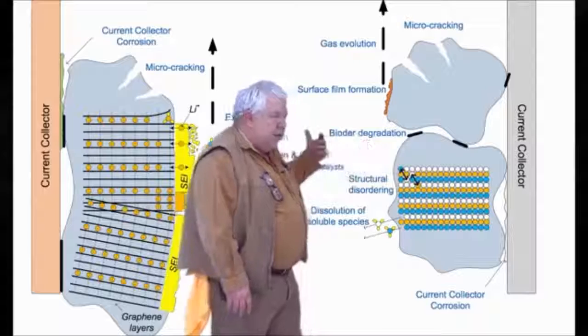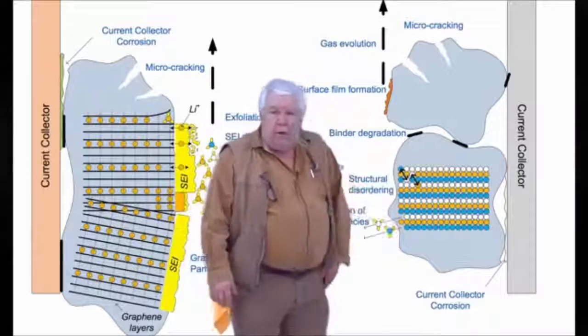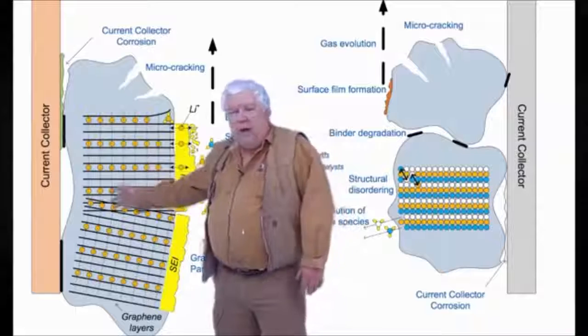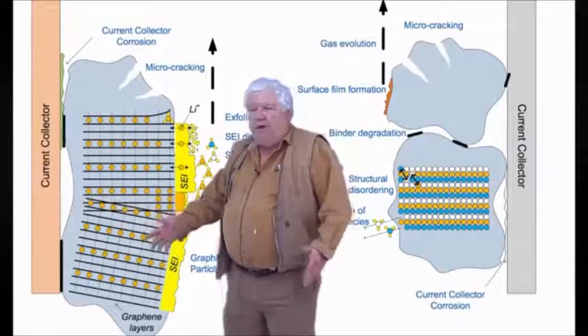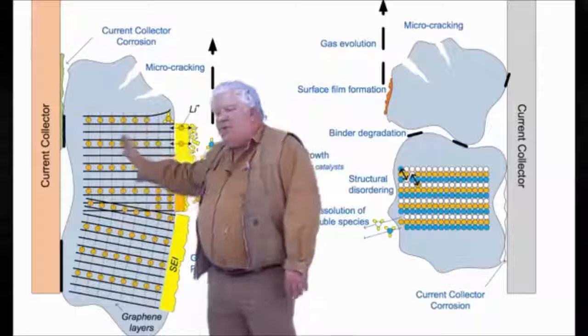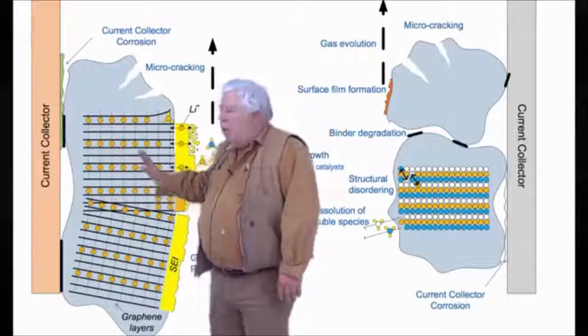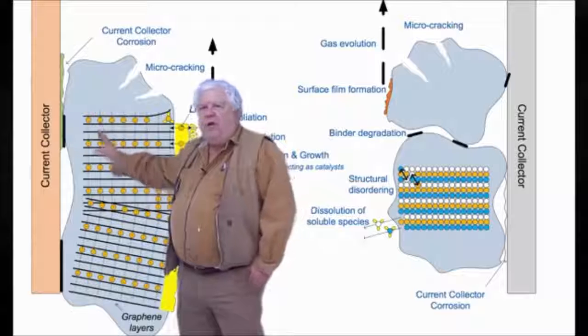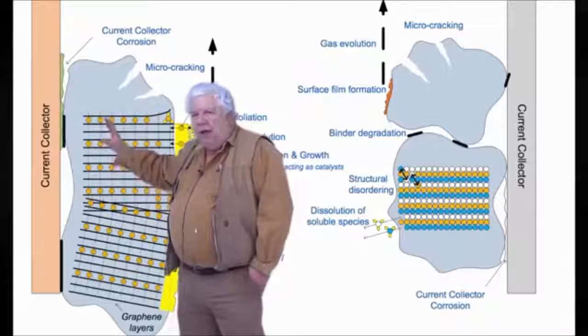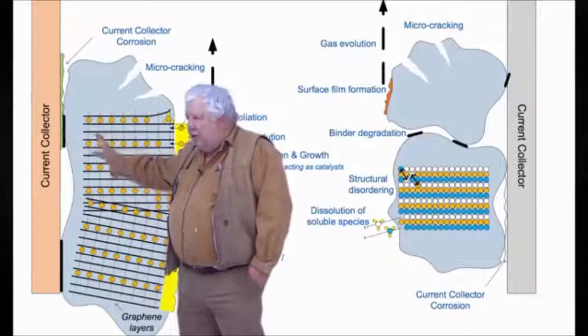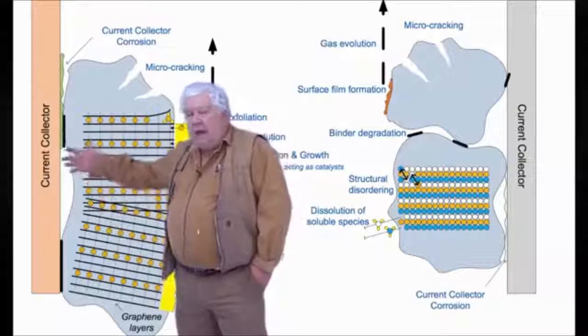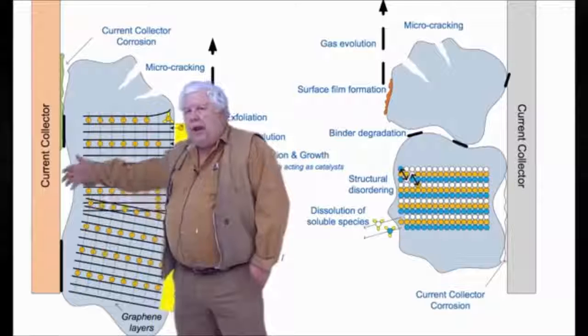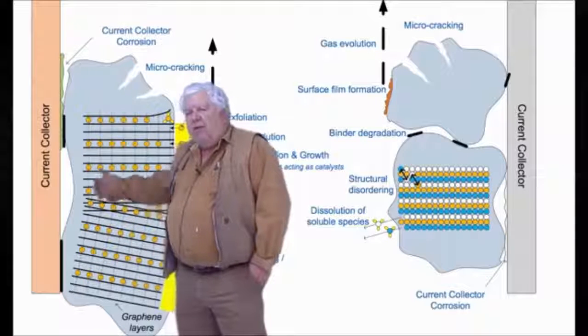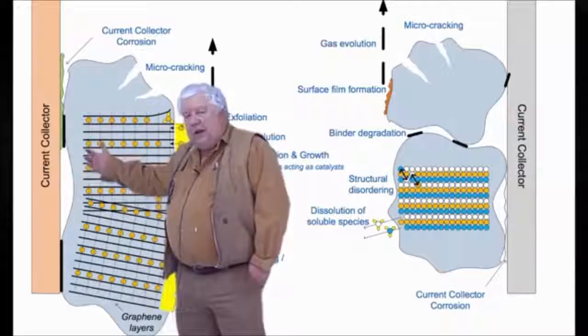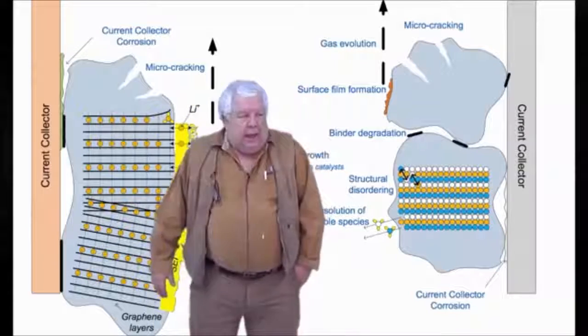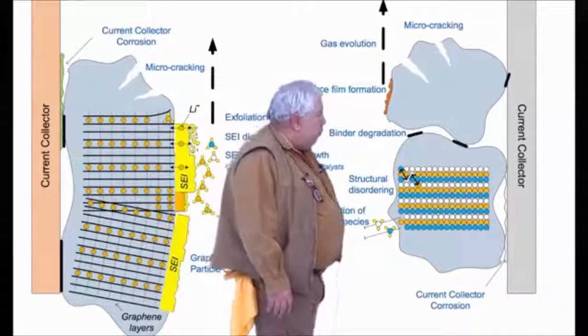You're still migrating lithium and perhaps iron from the cathode to the anode. That you're doing it slowly or fastly is not the point. The damage is really pretty much the same. It may be slower coming up to it, until this goes into cascade and you actually melt the SEI layer and dump. You could kind of sneak up on it for a while and do a lot of damage without actually getting into thermal because it's more gradual. But it's eventually going to go. And when it does, you go into thermal runaway.